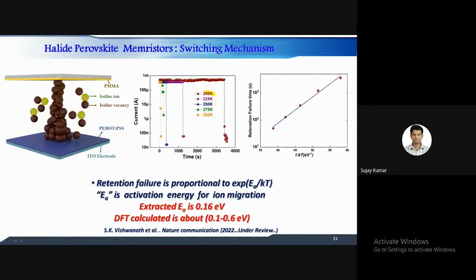In a metallic conductor, when you increase the temperature, the resistivity will go up. Here we observe a similar kind of thing. We found the activation energy for this particular conducting filament, which is around 0.16 electron volt, very comparable with the DFT-calculated iodine activation energy. This is what we did to understand the switching mechanism.